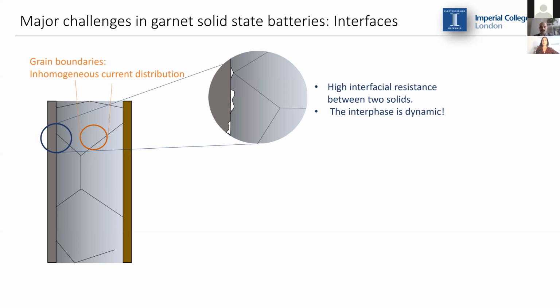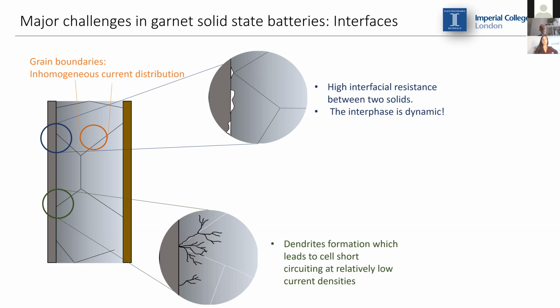The other interface of interest is the lithium metal with the garnet. I said before that it is kinetically stable, and it may not form an SEI layer that is leading to a higher resistance, but during cycling of the battery, this interface is very dynamic. Since we are stripping lithium, we can create voids that then don't recover, and so we can have a very inhomogeneous interface in terms of contact. All this inhomogeneous distribution of current sources that I am describing can lead to a very soon nucleation and propagation of lithium dendrites that eventually leads to a premature death of the cell.